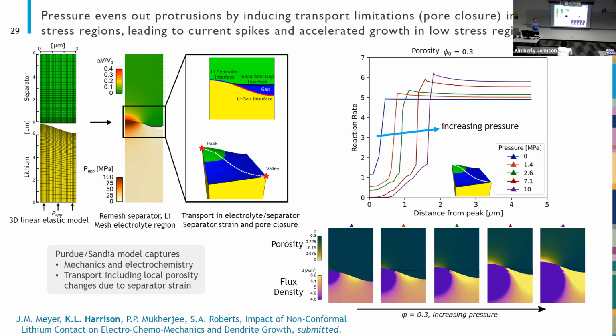And we know very well from the literature that lithium will plate in these dendritic morphologies at very high currents. And so if we have these current spikes, we're likely to get dendrites. And so we think that's why we were seeing at the highest pressures this unstable lithium plating, because we're shutting down transport and because we're forming dendrites.